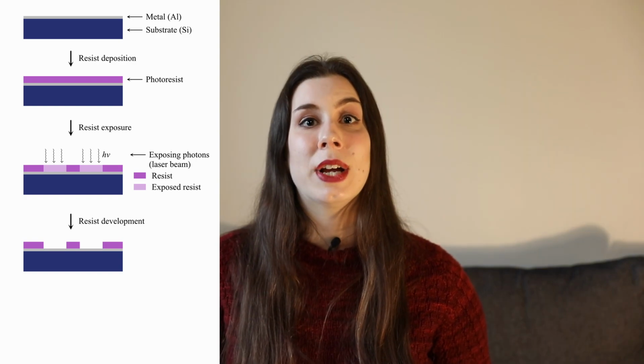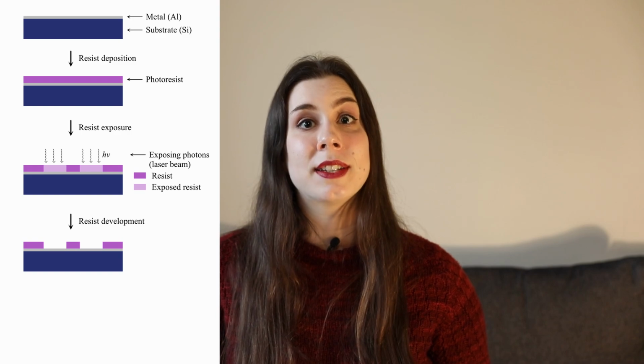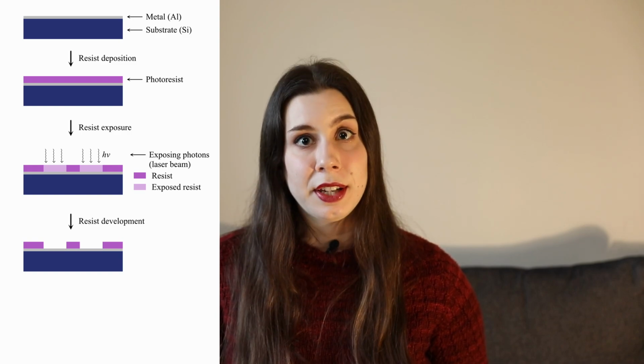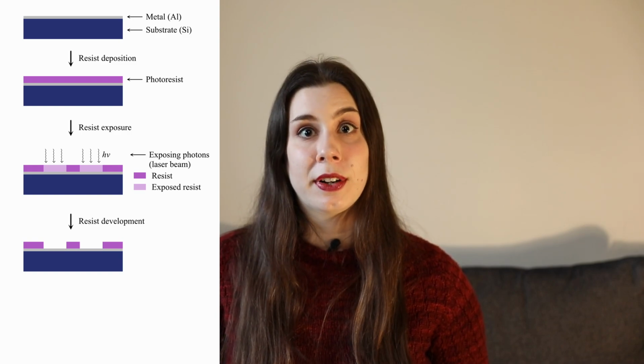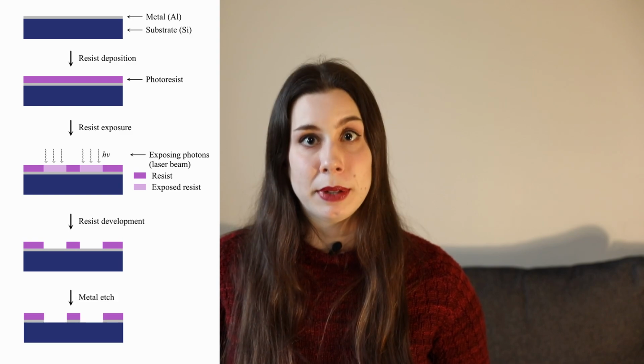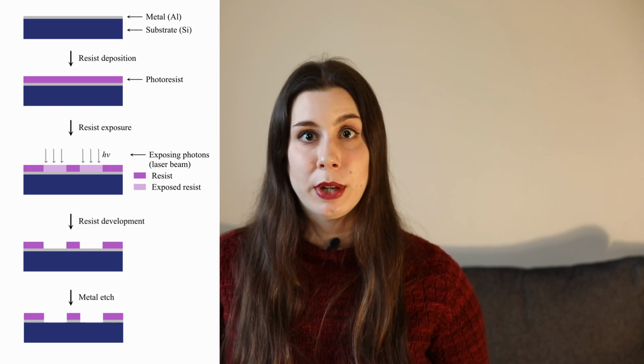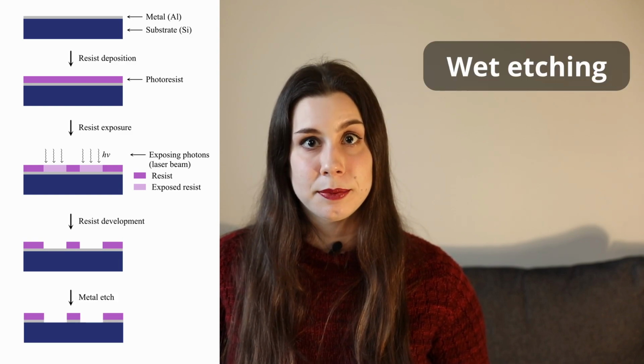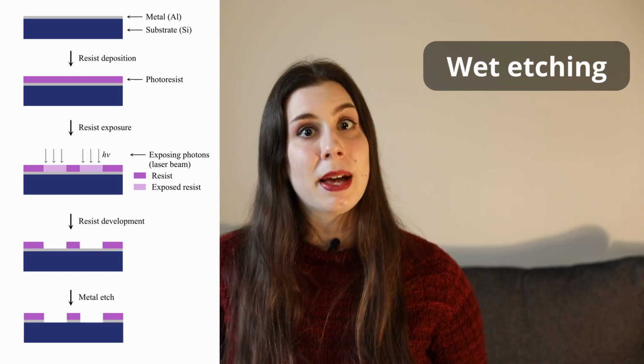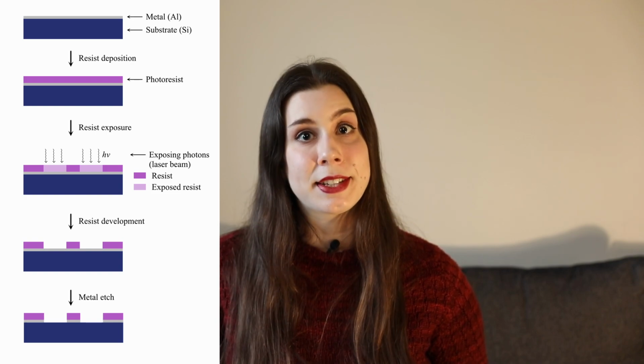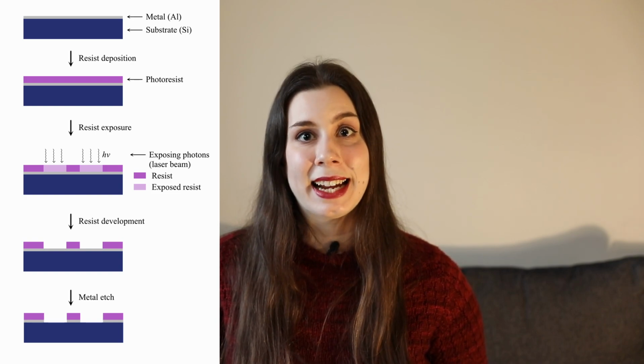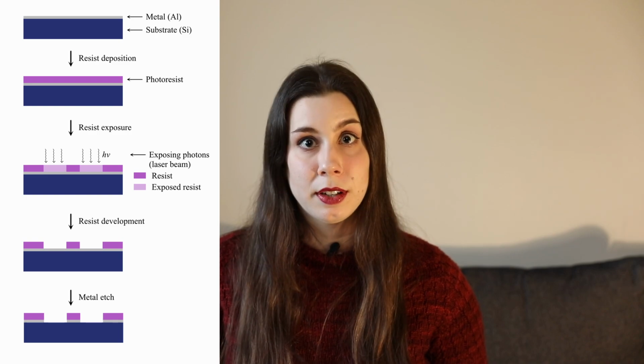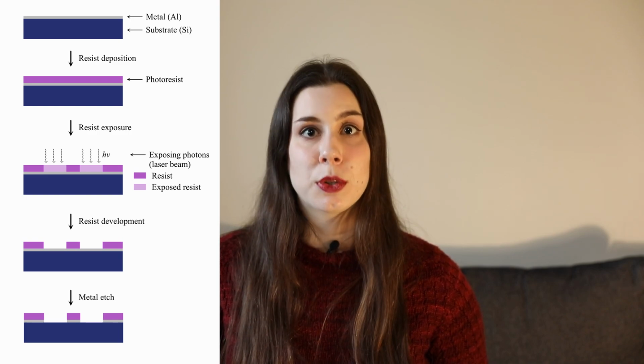When we then want to transfer the pattern defined in the photoresist layer into the actual metal underneath, we will simply submerge the wafer into an acid that reacts with aluminium, removing it from the surface of the wafer in a process called wet etching. The areas of aluminium that are covered by the remaining resist will be protected from this acid attack and will also remain on the wafer. The exposed pattern will be etched away.